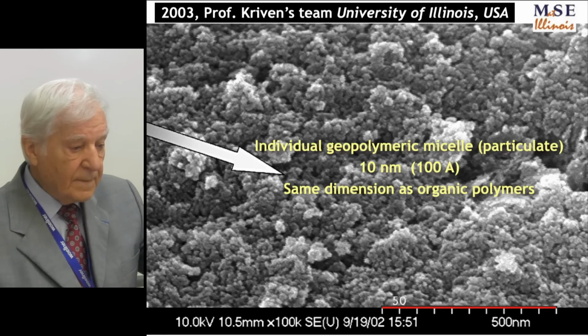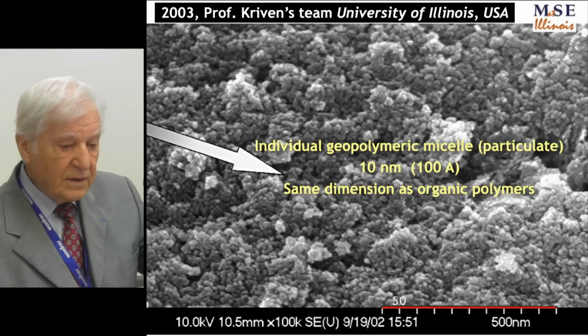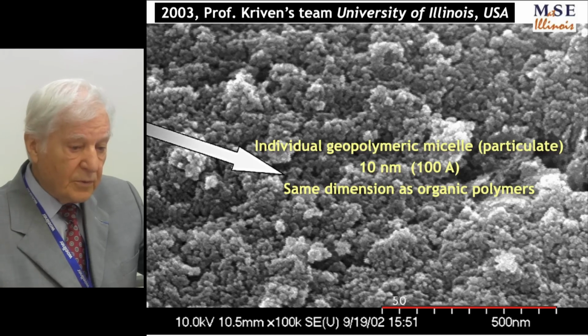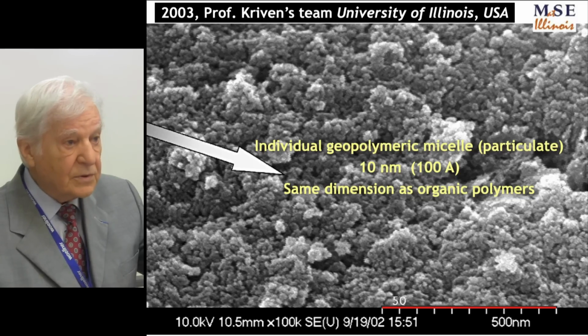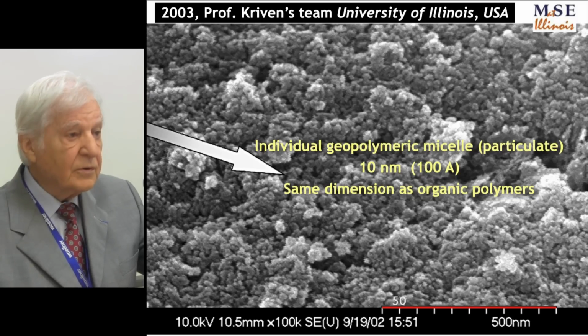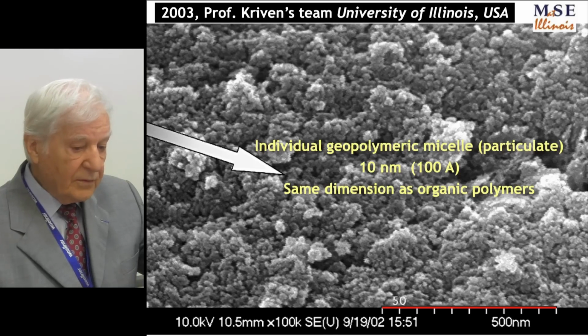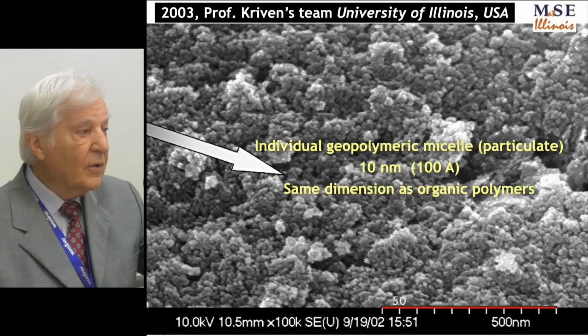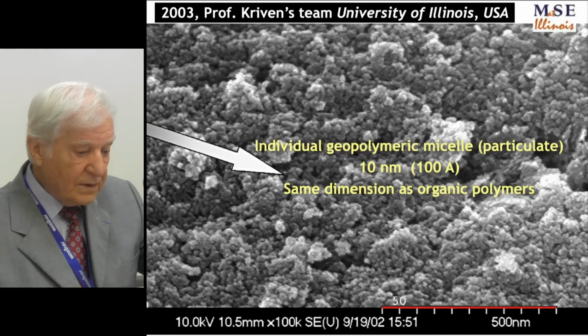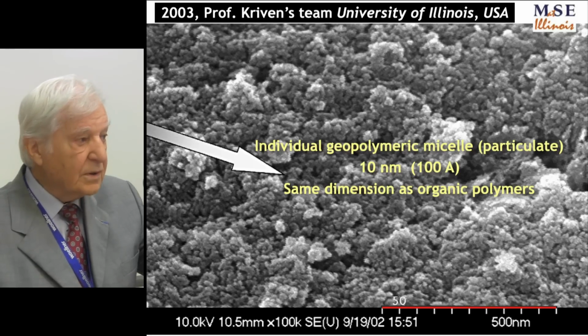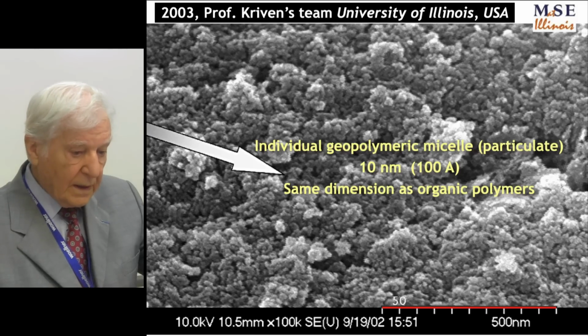In 2003, Waltraud Kriven and her team at the University of Illinois in the USA investigated with the scanning electron microscopy the microstructure of fully reacted potassium sialate siloxo type geopolymers. The geopolymer was the result of a sol-gel reaction. They found that it consists of individual nanoparticulates ranging from 10 to 20 nanometers in diameter. They are shown on the slides at the pointed tip of the arrow. The scale is 500 nanometers and the subscale is 50 nanometers.